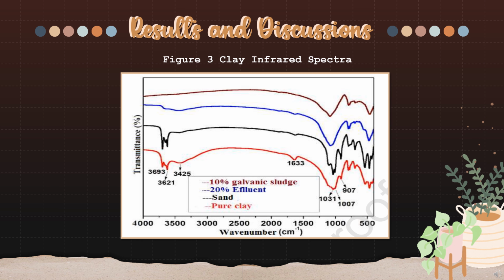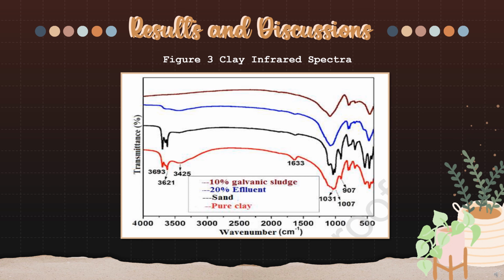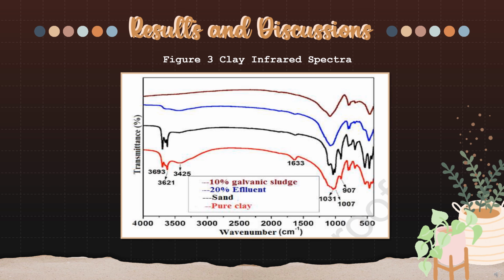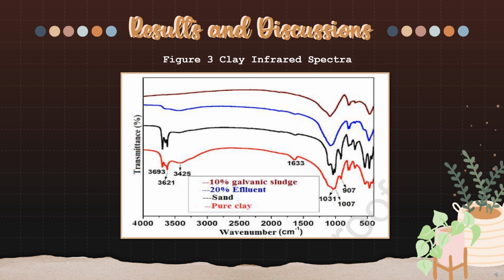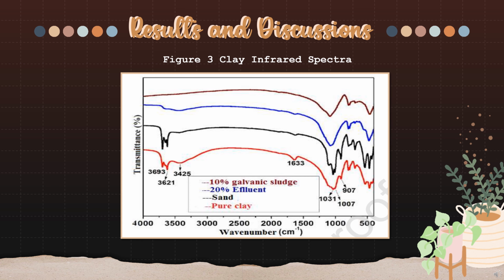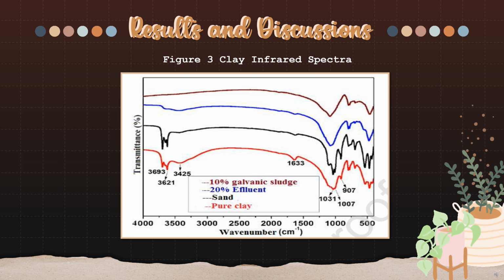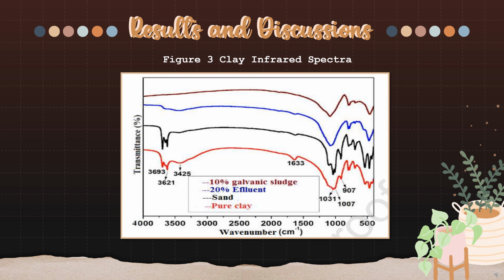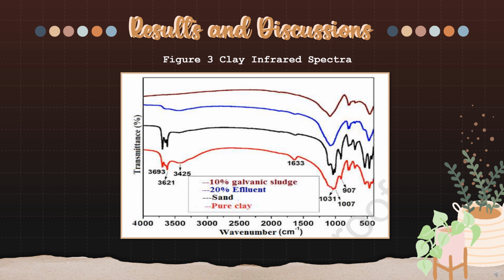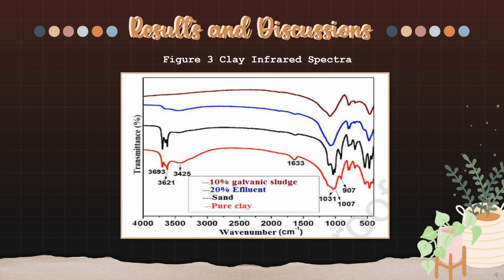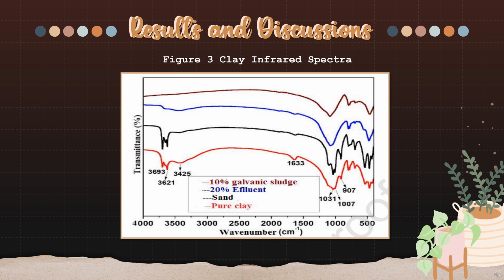The hydroxyl group internal to the clay mineral structure, or the OH group of the octahedral structure, is assigned to the band at 3,621. The free hydroxyl group, which is asymmetric in the hydrogen-oxygen-hydrogen bond vibration, is assigned to the band at 3,693. The hydroxyl stretching vibrations of the water absorbed internally to the clay structure correspond to the broad band at 3,425 per centimeter, and their corresponding bending vibrations are observed at about 1,630 per centimeter.